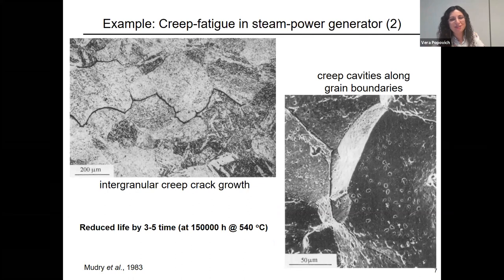As I come from a materials department, we for sure like to look inside the materials and design the materials for specific resistance. In this particular case, on the left-hand side image, you see a cross-section of that crack. That's what we call intergranular creep cracks along the grain boundaries. This cross-section, to reveal this, has been polished and etched. And you see a very distinct creep crack along the grain boundaries. You can also see a fracture surface on the right-hand side. So these are creep cavities on the grain boundaries that are perpendicular to the applied tensile axis, in this particular case.